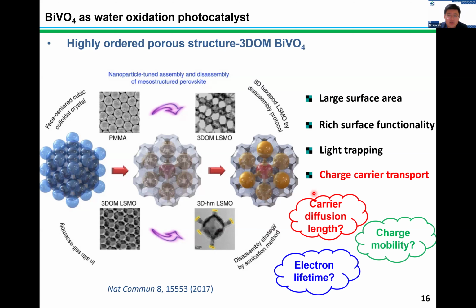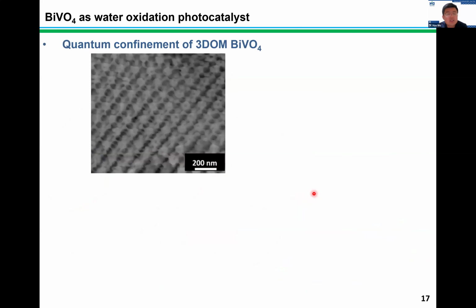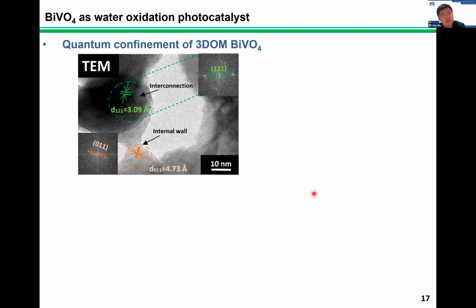So to answer that, we first synthesized the three-dimensional bismuth vanadate. From the TEM image, we can see the periodically ordered pores within our samples. And with the fine structure analysis, the first information that we would like to talk about is the ultra-thin internal wall of the structure. When we synthesize the catalyst into the nano regime, such as 5 to 10 nanometers, it generally shows the quantum confinement effect, which could enlarge the band gap of the semiconductor and increase the thermodynamic power of